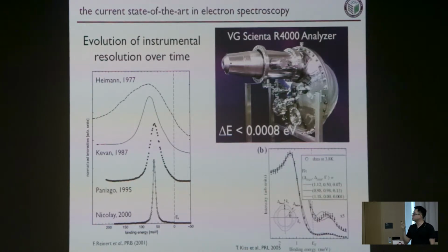And so, like I said, because you can get down to very high energy resolution, this is less than 1 millielectron volt. With a cryostat, we can get down to temperature, the best people have done is down to a couple Kelvin. So you can measure now, for instance, the superconducting gap in some low temperature superconductor where you can see that there's some shift away from the Fermi level. This is in millielectron volts by, let's say, half a millielectron volt. This is a very challenging measurement, but it's an example of what can be done with this technique if you're interested in these kinds of problems.